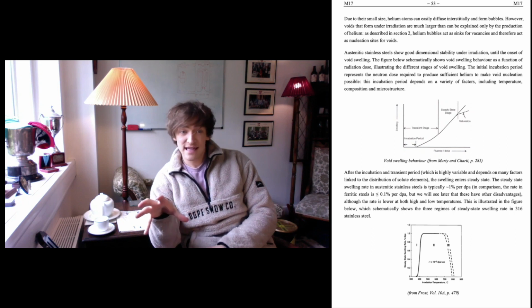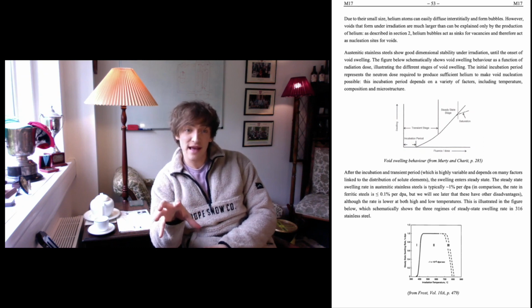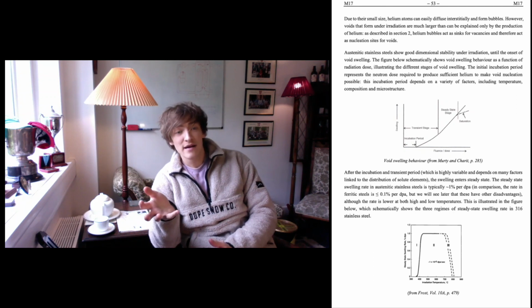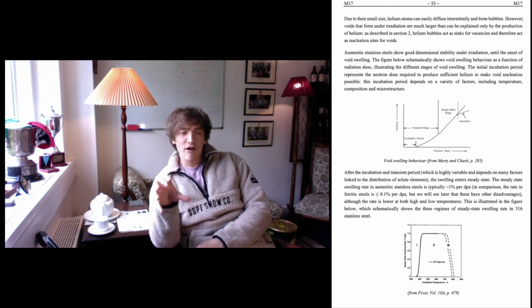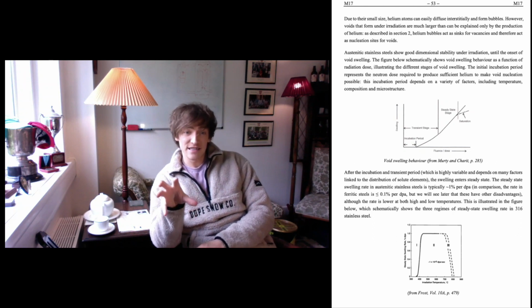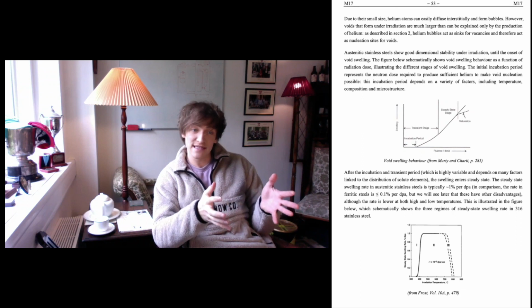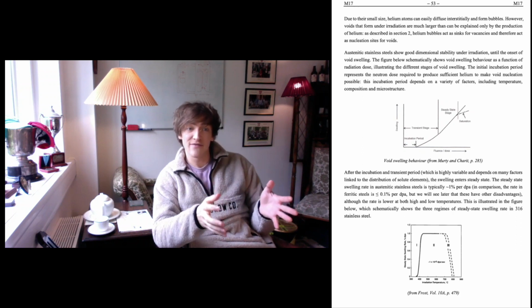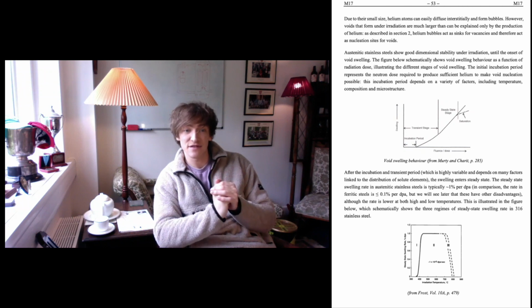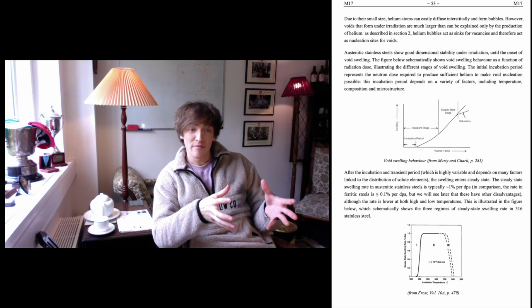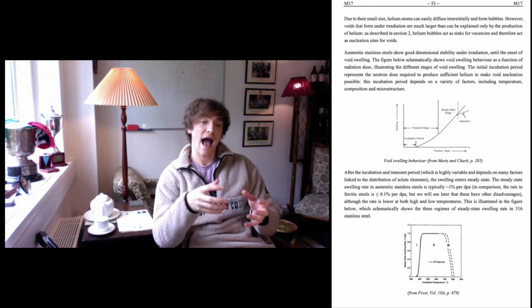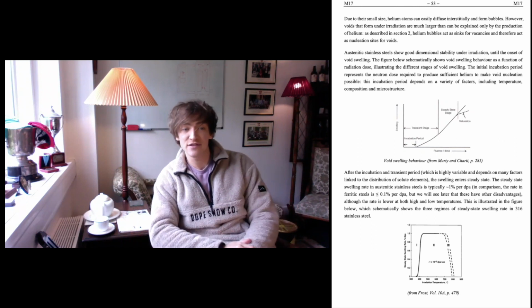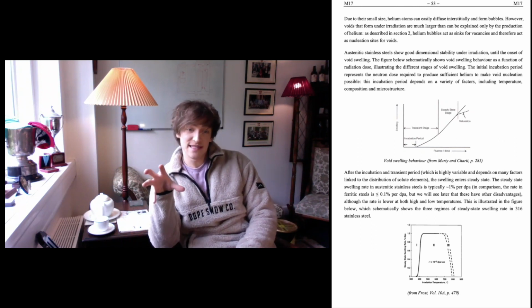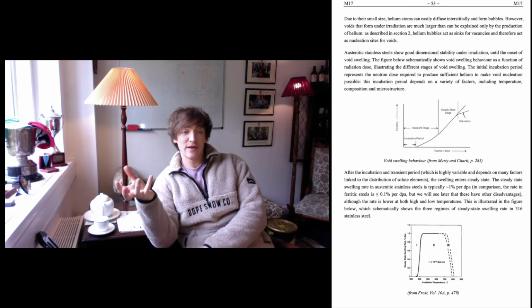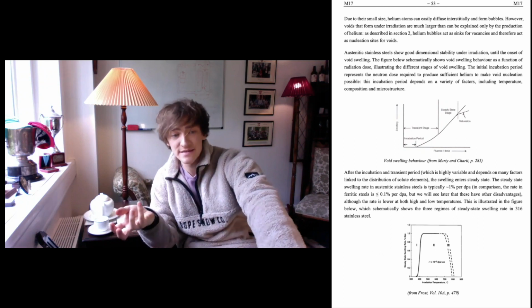For 316 stainless steel at least, that graph shows you got low swelling at high and low temperature, but high swelling at moderate temperatures. Why? Well, the low temperature state involves direct recombination of vacancies and interstitials because they've got lower mobilities at lower temperatures. So the swelling rate is therefore low, but increases gradually with increasing temperature as you increase the mobility of your vacancies and your interstitials. And at moderate temperatures, the steady state swelling rate is high and can only be explained by an excess of vacancies.